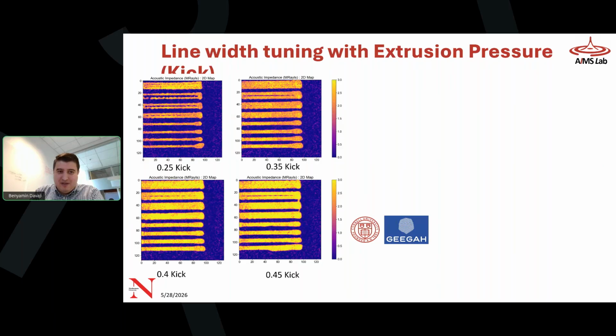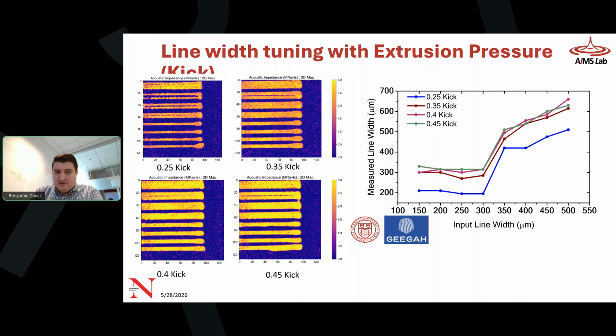You can see there is a parameter in extrusion printing that has something to do with pressure, how hard you are pushing the ink out. By pushing it harder or softer, you can tune the amount of ink coming out. By changing the combination of the pressure and the height of the nozzle to the substrate, you get a different profile. You can measure the acoustic impedance of that profile in real time, and using that, you can see different parameters will have a different impact, and over different features that scales also differently.